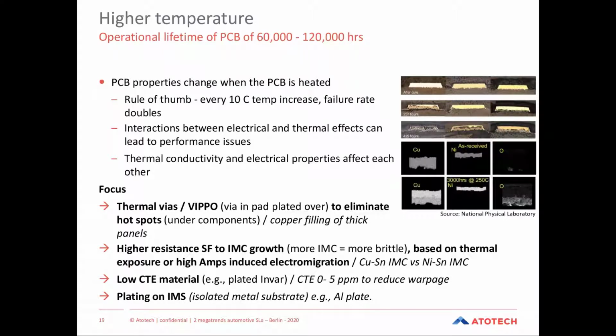A technology being used for packaged substrates since many years is copper through via filling. So we're filling the through vias completely with copper. And this technology is being tested today for PCBs to further improve heat dissipation under hotspots. Copper through via filling got attention also for PCBs, as it shows a 2.7 times faster heat transfer rate compared to epoxy-filled vias. And at the same time, the electrical resistance drops by 20%.